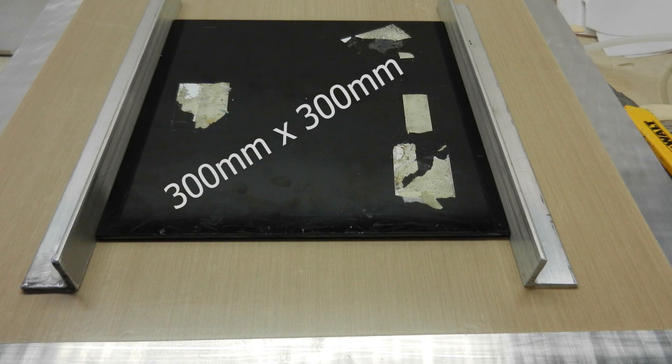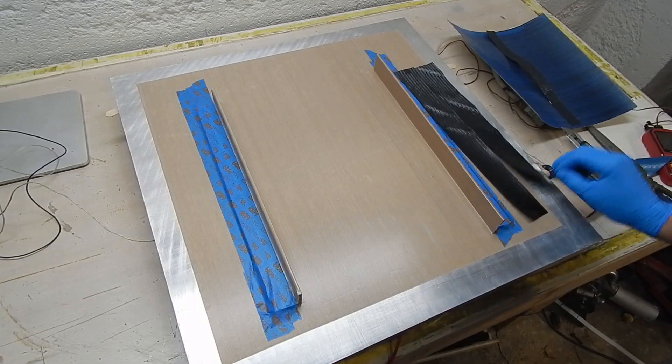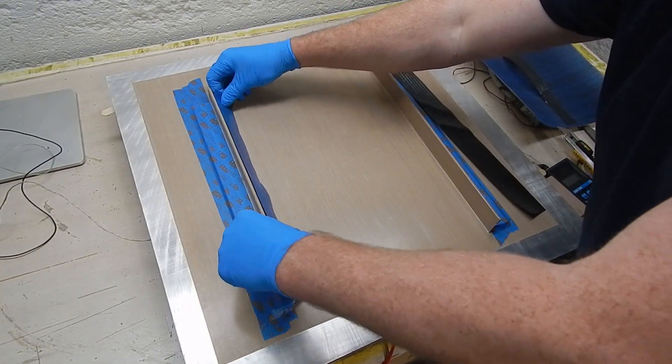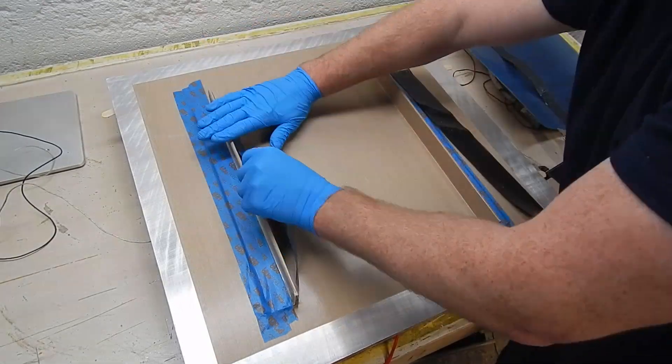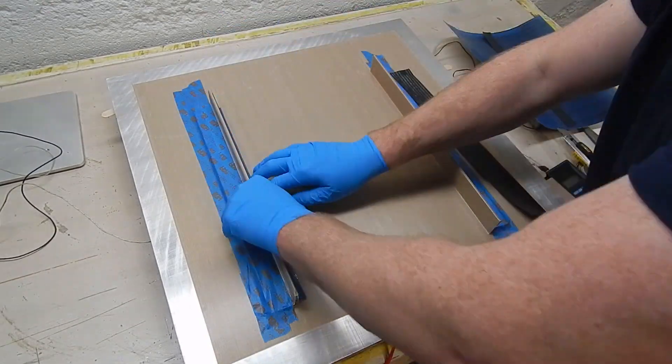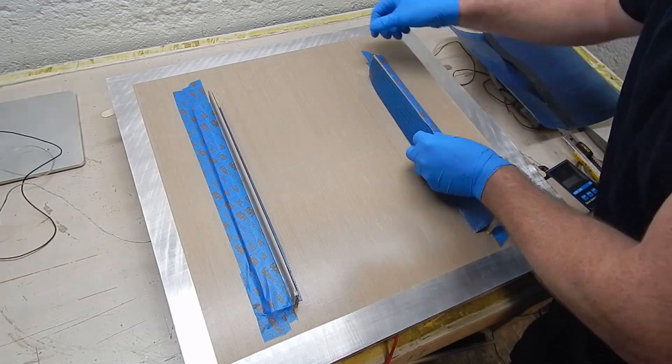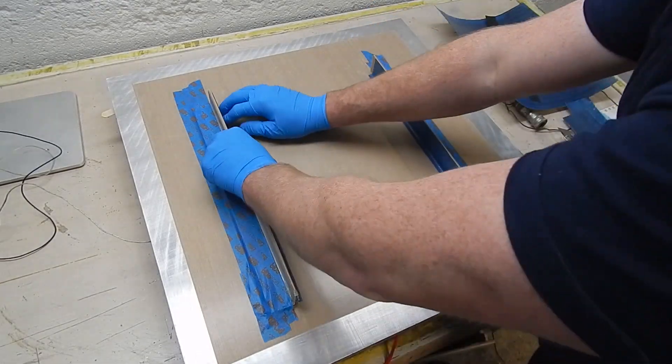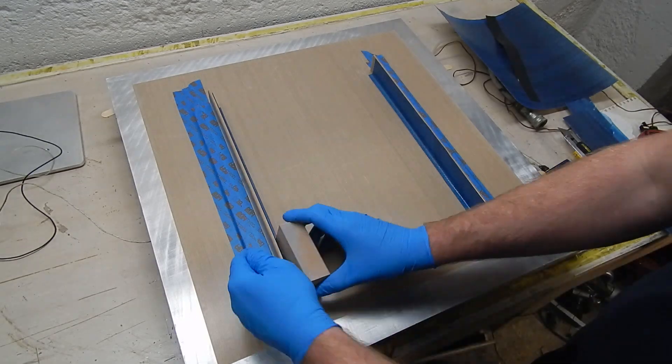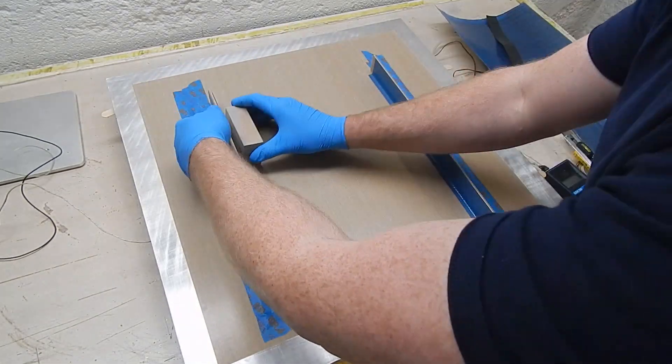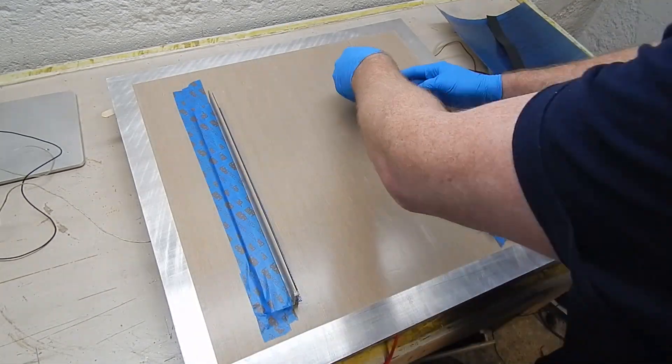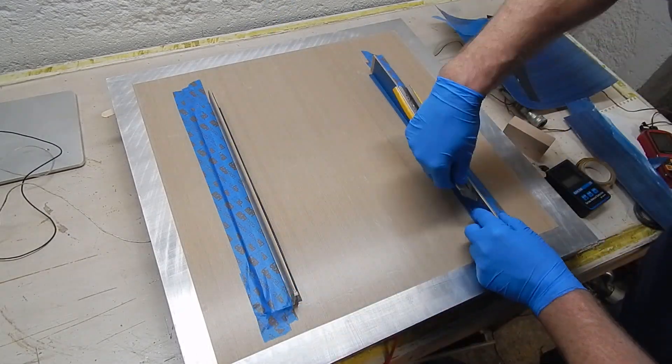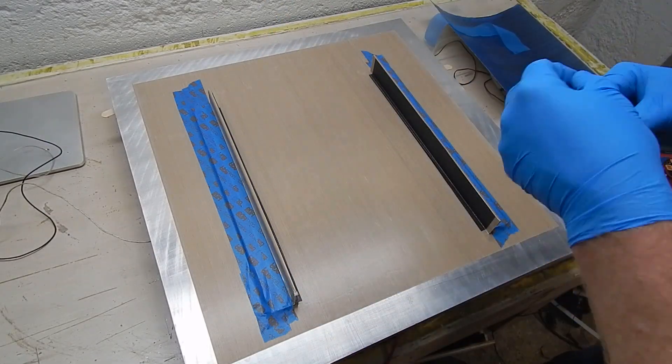And I made the panel by placing two aluminum angles on some double stick tape to form the flanges, then covering them with some Teflon. These are two plus or minus 45 strips of 200 gram woven, and I'm pressing them into the corner with a block. This is a very sharp corner because I didn't put any fillet strips.